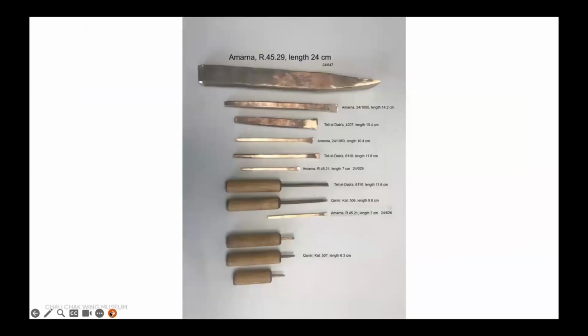So based on this research, Jury produced for us a group of replica chisels, some duplicates with and without wooden handles, from a tin bronze alloy with a tin content of 6 to 10%. So that's a higher tin content than Hemi-Ra, between about 1.5 to 5.5%, which we used as part of our second experiment, which took place on the 23rd of May last year.